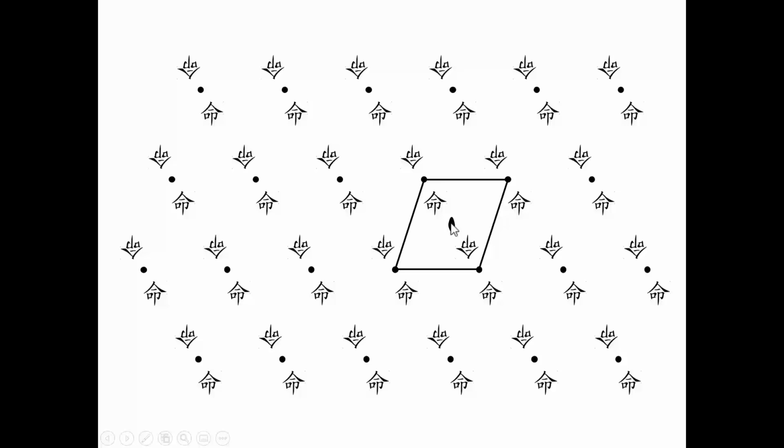First of all is now this 2-fold rotation axis has to operate not only on just these 2 characters that are inside the unit cell, but it has to be applicable to all of the characters in the infinite array of characters. And so you can see that's true. If I were to, let's say, operate the 2-fold rotation axis on this character, it's going to end up down here. If I were to operate it on this character, it's going to end up down here. So the application of translational symmetry here has not destroyed that twofold rotation axis.